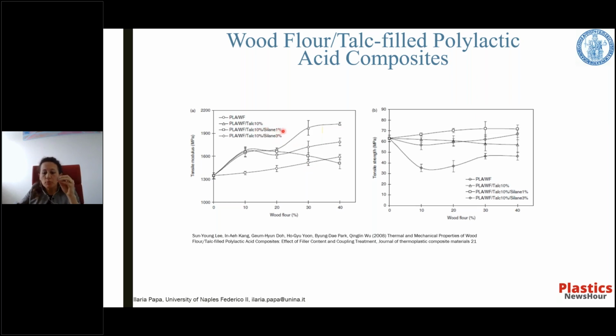Therefore, the presence of silane improves the compatibility of the PLA matrix and the wood flour and the talc. And so, as in the case of Young's modulus, but only for 1% of the silane. It is therefore observed that the use of natural fibers can lead to improvements in mechanical properties compared to the PLA, but the difficulties of coupling the PLA matrix and fibers are now the main obstacles to overcome to obtain wider application.